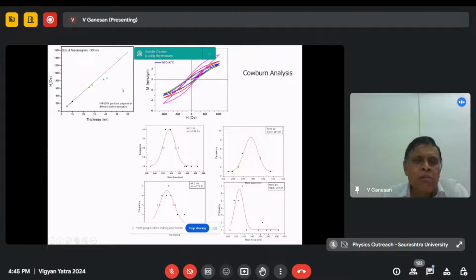But you see, the chemical methods produce such uniform particles. Whatever size, about submicron, about 100 or 50 nanometers, you can control the size. Every particle looks the same. That's very interesting. And then we tried to do a small magnetization measurement from them. From there, you can calculate the coercivity and you can plot it as a function of temperature. And these are ferrite particles. For some time it obeys a fitting, and after a certain bulk size, it won't obey nanomagnetism anymore. So the size-dependent magnetization can be studied. It was studied once upon a time.